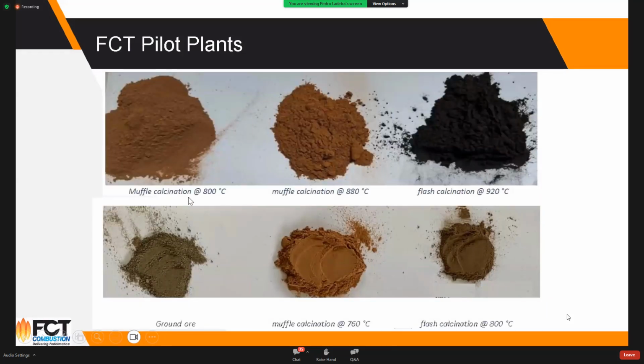This is when you do muffle calcination in an oxidizing way, and at different temperatures. But when you flash it at high temperature with the right inorganic modifier, you can have a pretty dark product. So the same happens when you get the ore and you muffle calcine it, it gets red. When you flash calcine, you can get the material with less of this red hue.